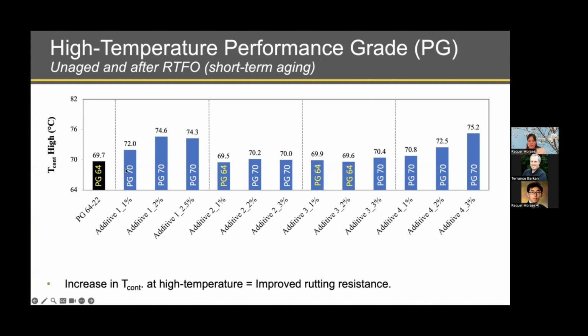As mentioned in the slide before, for some of the additives, we saw 1 grade bump. Initially, the binder was classified as PG64, but after incorporation of the graphene, the binder ended up being a PG70. For some of the binders, specifically additive 2 at 1% and additive 3 at 1 and 2%, no change in the PG grade of the binder was observed. It remains 64.